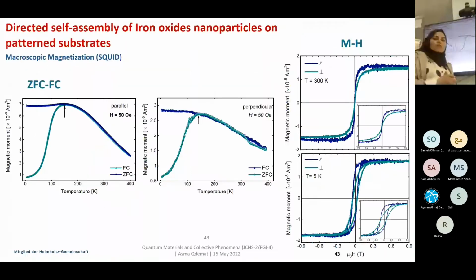The last thing about this system, I tried to study its magnetic properties, and again I performed zero field cooling, magnetization as a function of temperature, and magnetization as a function of the field. From magnetization as a function of temperature, in both directions, along the lines and perpendicular to the lines, we can see that along the lines it shows a higher magnetic moment than perpendicular to the lines, which is an indication of an in-plane easy axis, where the particles are energetically favorable to align along the lines. We can also see a decrease in the field cooling curve, which is due to the magnetic interaction between the nanoparticles, which we could not obtain in the perpendicular direction.